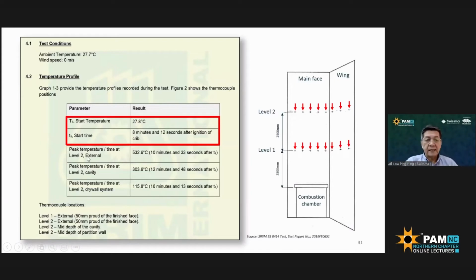In this test, the peak temperature recorded was 532.6 degrees Celsius, achieved at 10 minutes, 33 seconds after ts. The cavity temperature was lower, 303, and the thermocouple inside the drywall was very much lower, as expected. So this will give you a clear picture of how these measurements are done. They have a benchmark based on the start time ts.